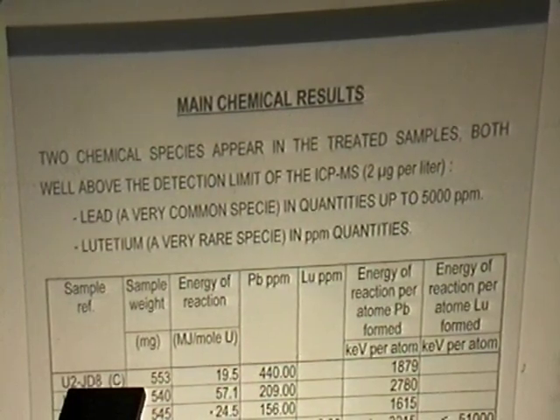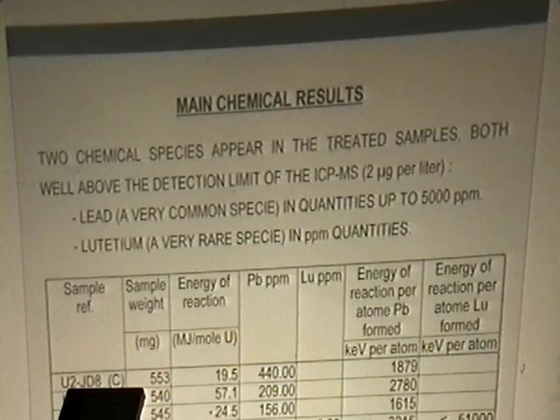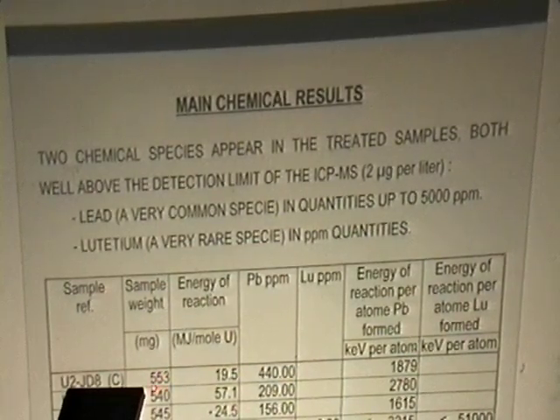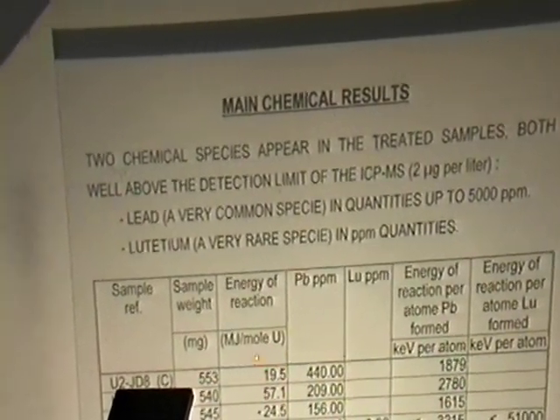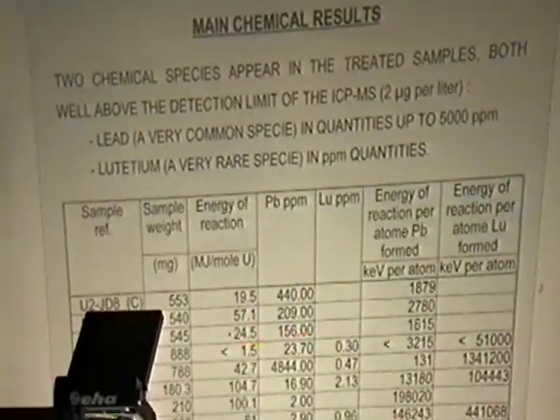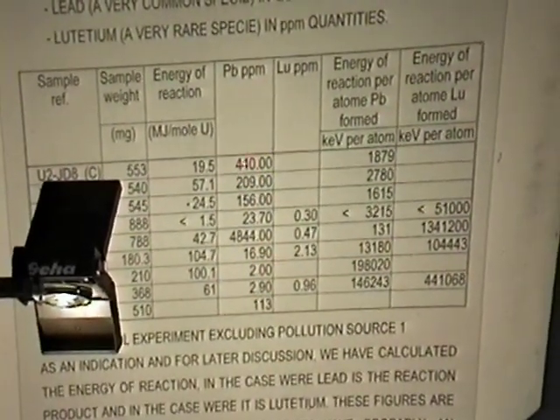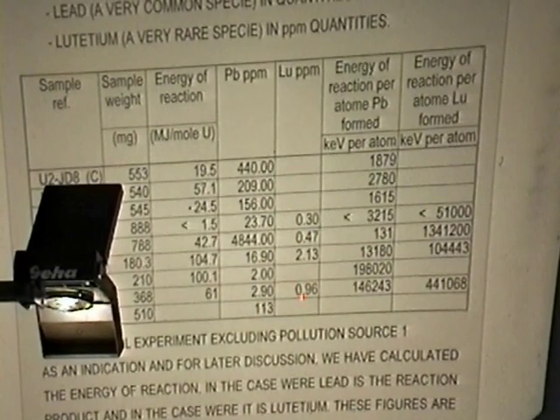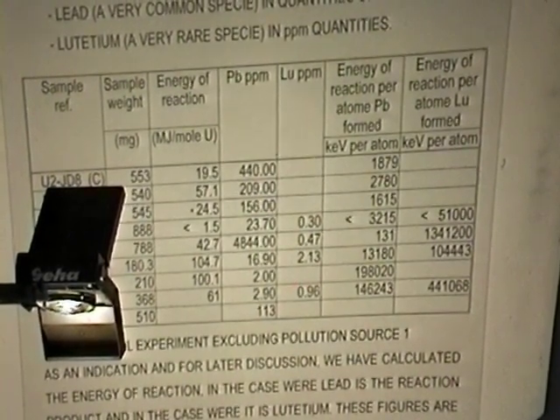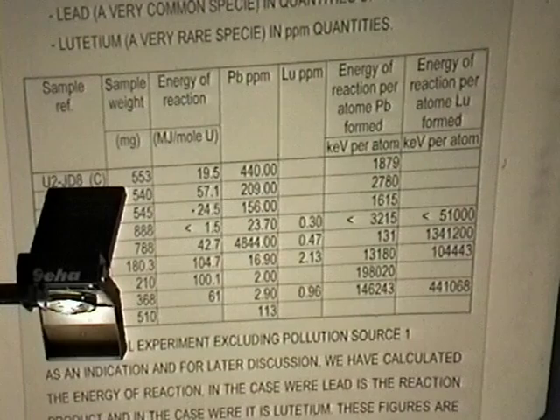So you can see that the sample treatment varies from 200 to 500 milligrams. The energy of reaction was calculated previously. So these are the results in ppm of lead, and these are ppm of lutetium. So to try to understand what happens, you can divide the energy observed by the number of atoms of lead formed, and you can also divide it by the number of lutetium formed.